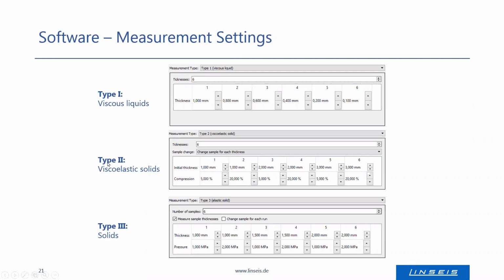For type 2, the viscoelastic solids, one typically defines a compression which refers to initial thickness. Like in this example, one had samples with thickness 1, 2, and 3 millimeters, and defined each a compression of 5 and 20%.